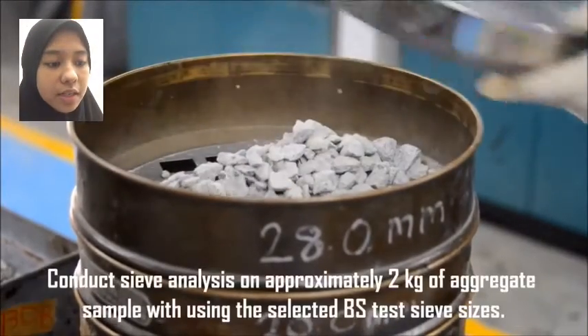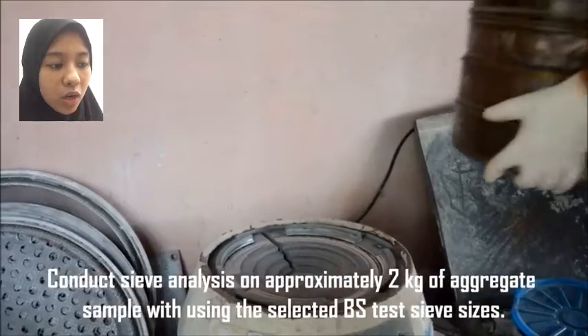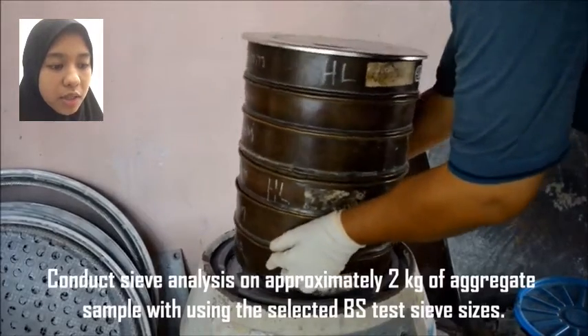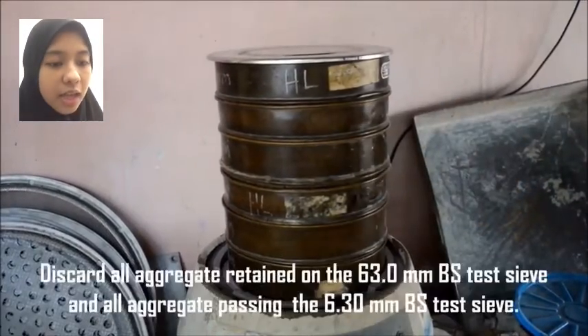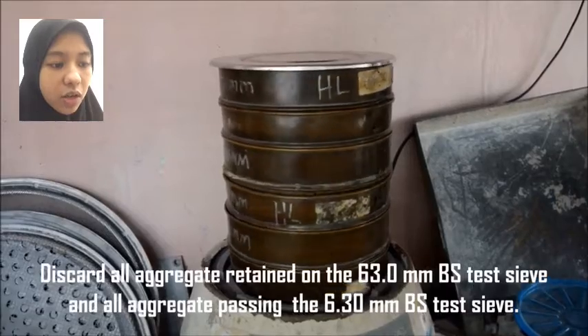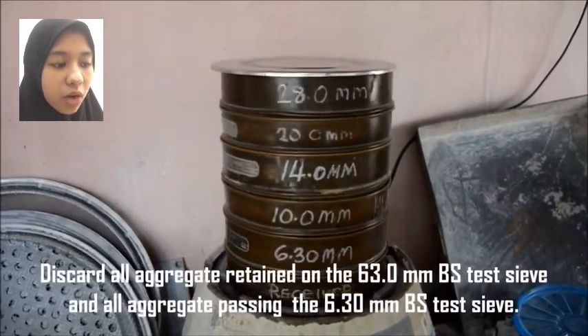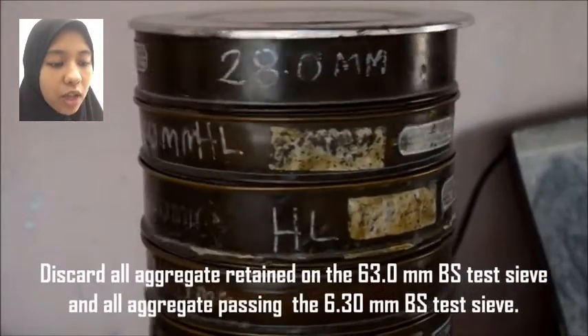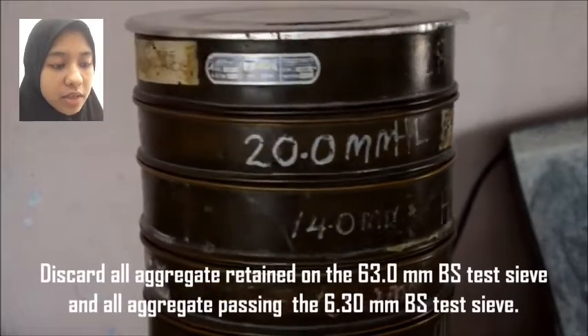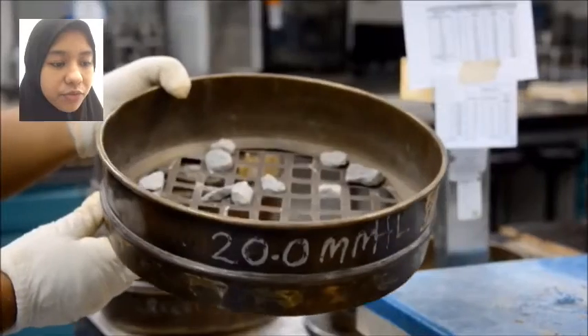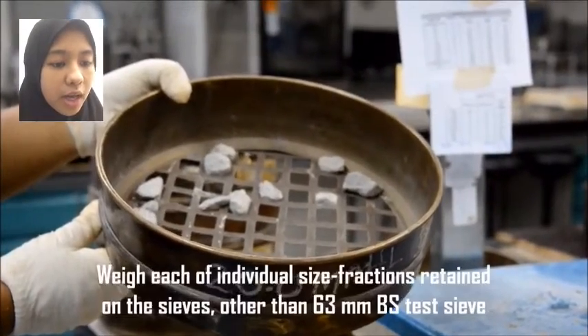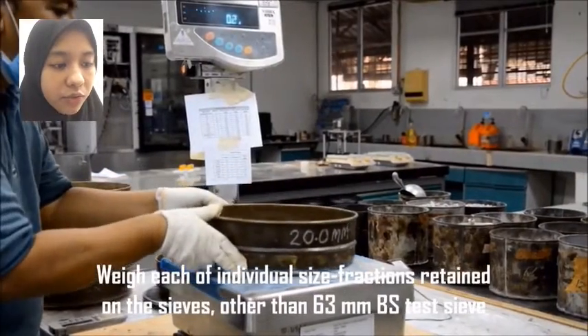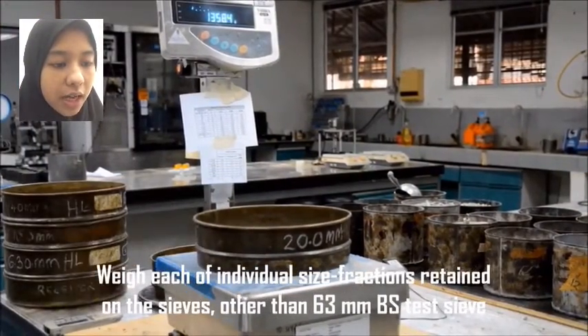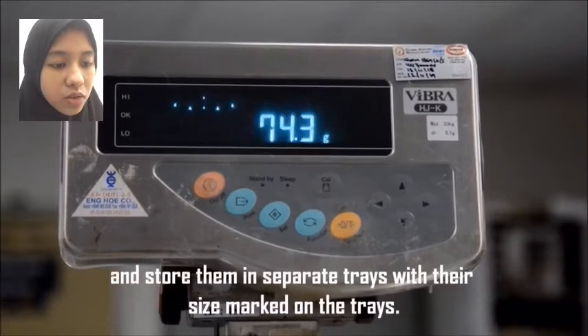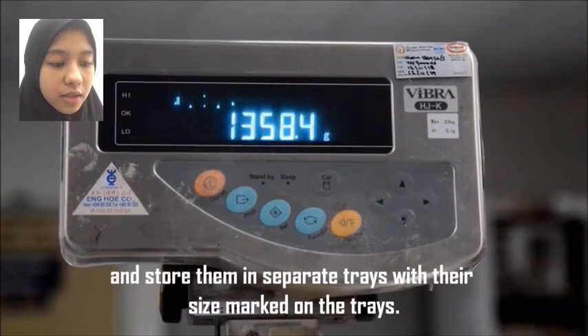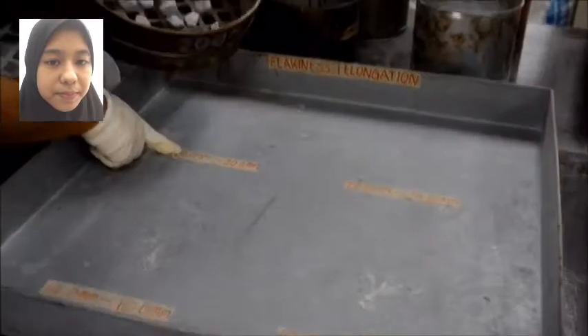Conduct sieve analysis on approximately 2 kg of aggregate sample using the selected BS test sieves. Discard all the aggregate retained on the 63.0 mm BS test sieve and all aggregate passing the 6.30 mm BS test sieve. Weigh each of the individual size fractions retained on the sieves other than 63 mm and store them in separate trays with their sizes marked on the trays.